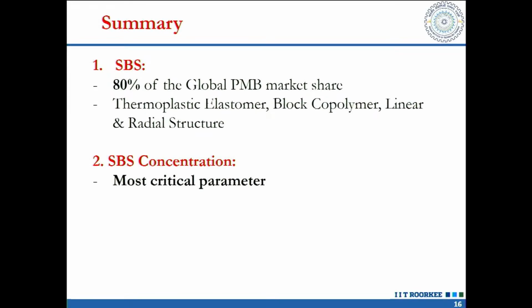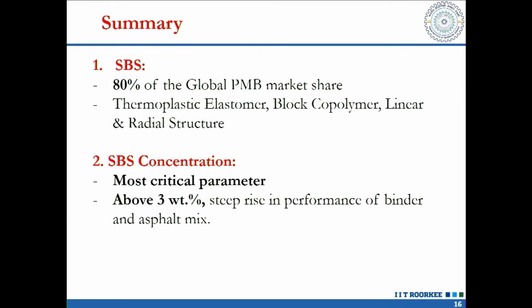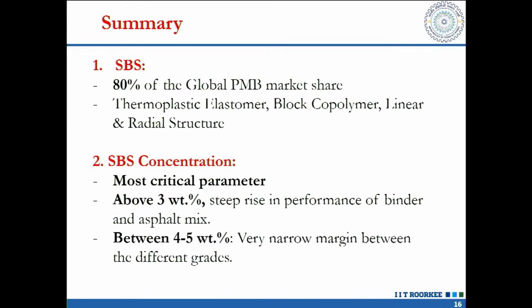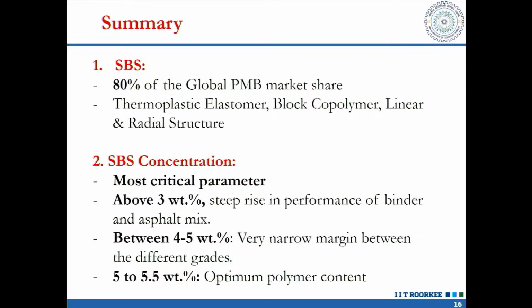And in all cases of PMB, the concentration of the polymer plays the most pivotal role. And the moment there is a network created by the polymer, the properties greatly enhance. So the first important point to understand is that a network has to be created within the bitumen. And that can be formed in SBS only above 3 weight percent. And I would suggest at least use an SBS PMB with 4.5 to 5 weight percent of the polymer in the bitumen. This is the most critical component. The moment you say, sir, we are using SBS modified bitumen, but properties are not coming in the mixture, it won't come as long as you do not go to a concentration of 4.5 to 5%. This is the most critical component.